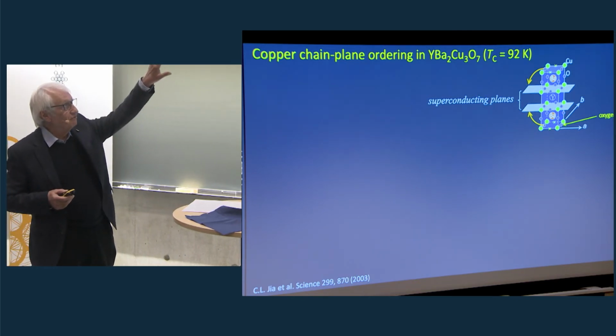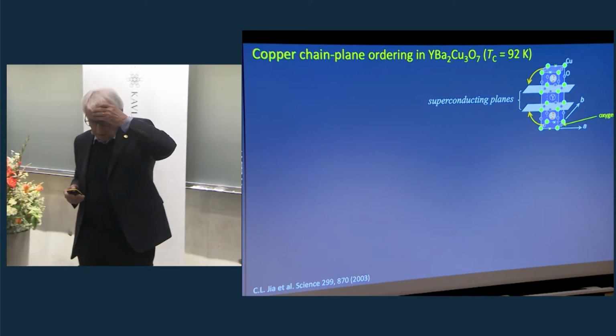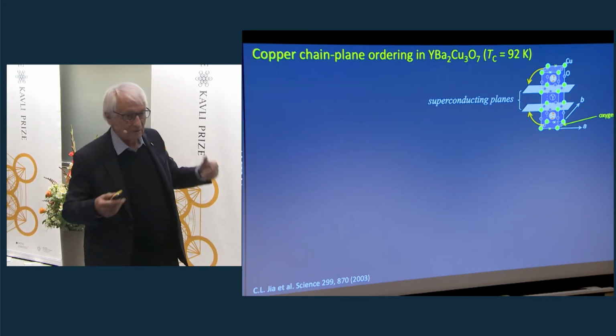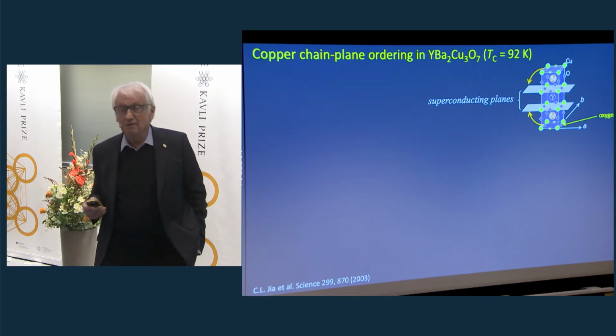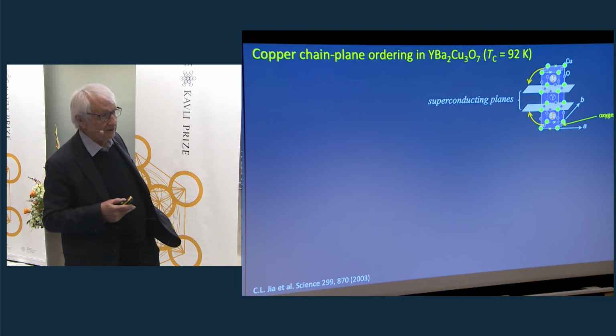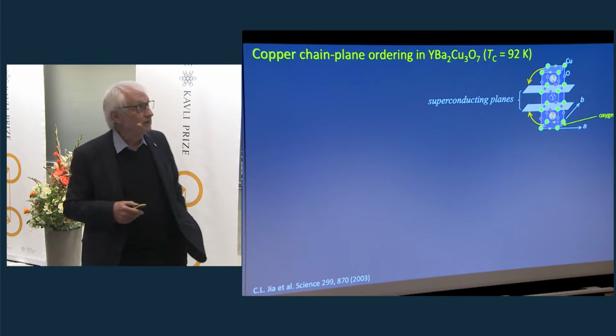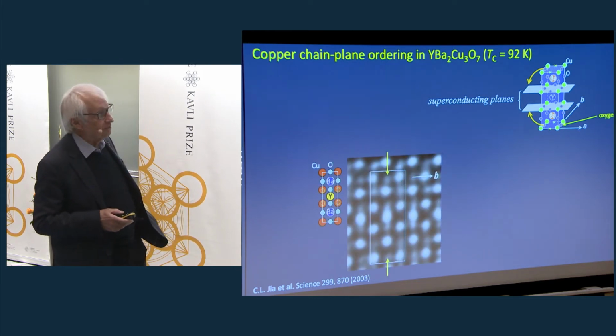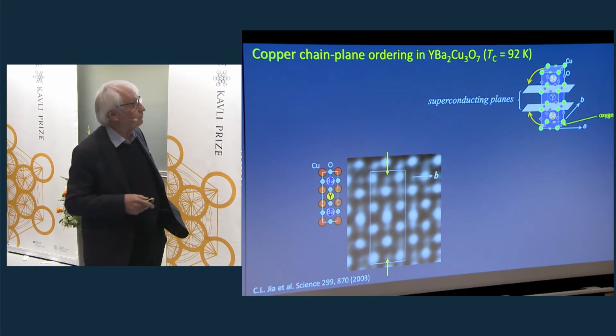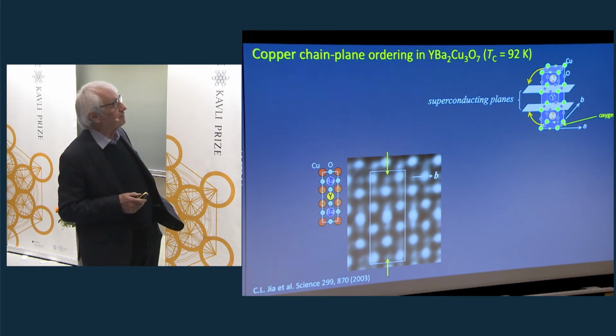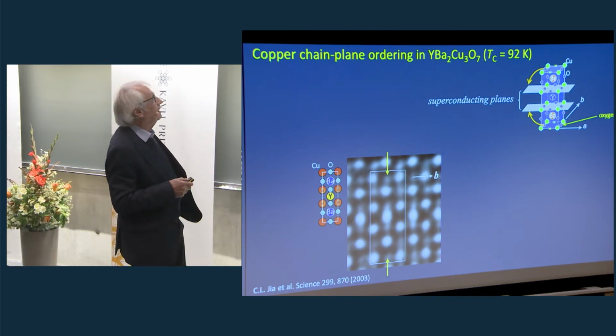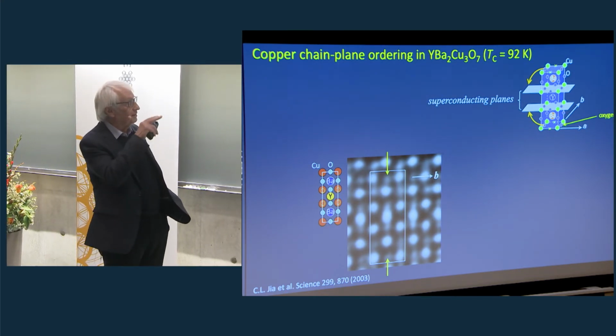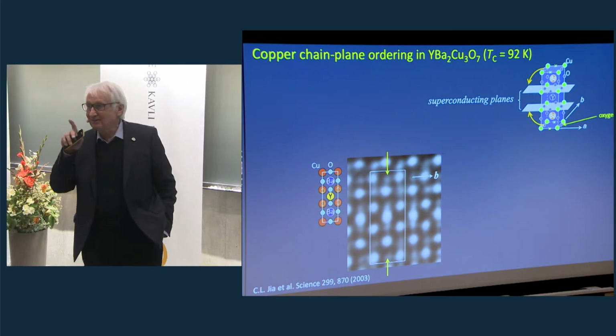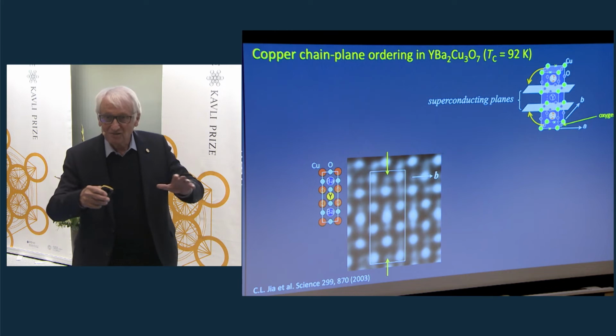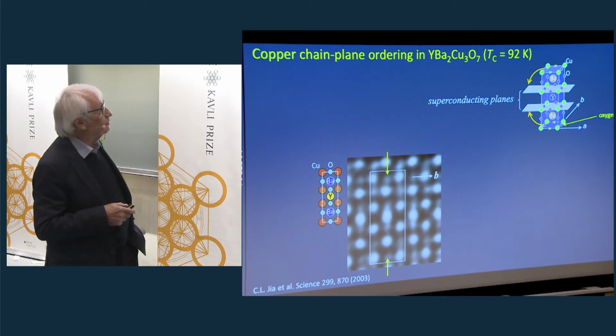And at that time, when we did the first experiments with yttrium barium copper oxide, of course, aberration-corrected microscopy was not available, and we had no chance to see whether these sites were occupied or not. So, after about 15, 20 years later, when the aberration-corrected microscope was available, we put a sample into the microscope, calculated the conditions so that we have essentially a view which is easy to interpret.